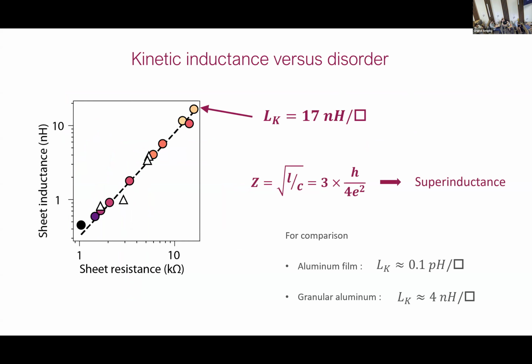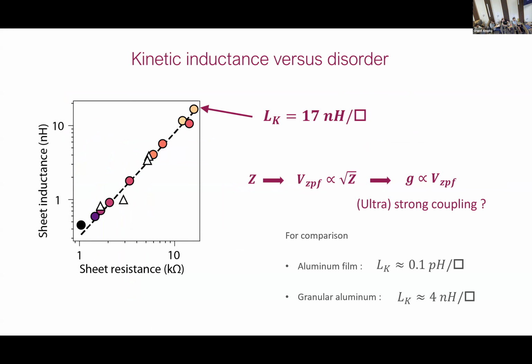What is also interesting here is that this impedance matters also for circuit quantum electrodynamic schemes, because the zero-point fluctuations of the voltages, if you do a resonator, scale like the square root of Z. And as I said, this number is huge when you are very disordered or you have a very low superfluid density. Then you can also engineer strong coupling to any charge dipoles in that situation. That is interesting because you have tons of things that you can possibly couple, perhaps in a strong way, to such kinds of resonators.